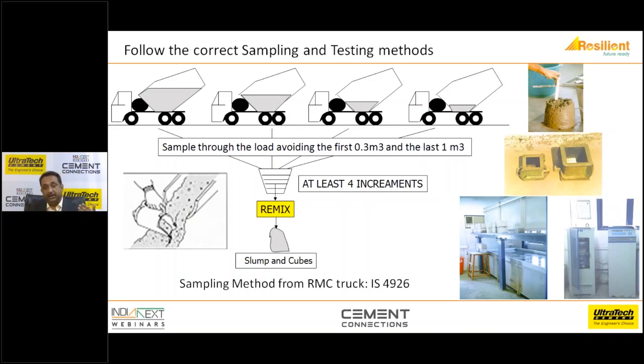It's also important to know the direction in which you actually do the sampling. What you see on the left in the middle is the right sampling with the scoop, which is perpendicular to the flow of the concrete. Using the right cube molds, using the right curing, using the right testing, the test machines are all important to ensure that you get results which reflect the quality of concrete. Otherwise, in a dispute you'll be barking up the wrong tree, because in the first place, the result itself is not proper.